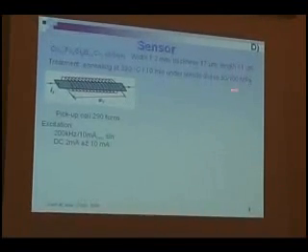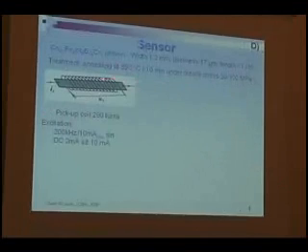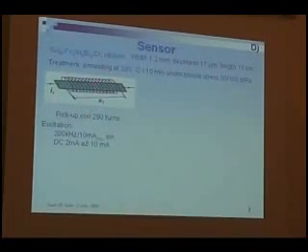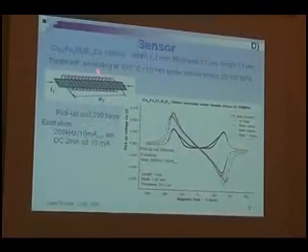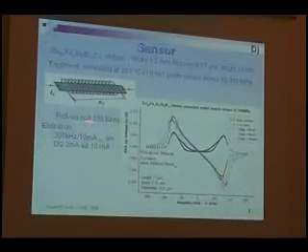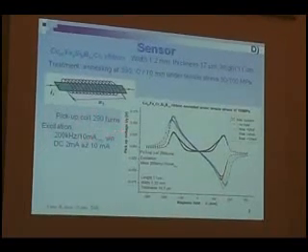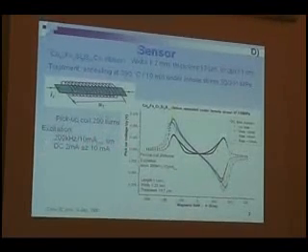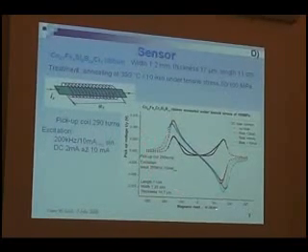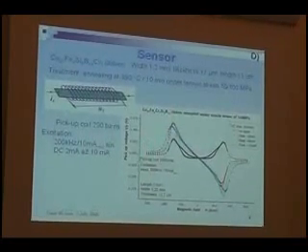We used the ribbon with this composition, annealed under 50 megapascals and 100 megapascals. So the sensor itself is very easy. There is only a ribbon and the pickup coil. And for these conditions, 200 kilohertz, 10 milliamps RMS sine wave signal, and for DC current from 0 up to 10 milliamps, we observed those responses.